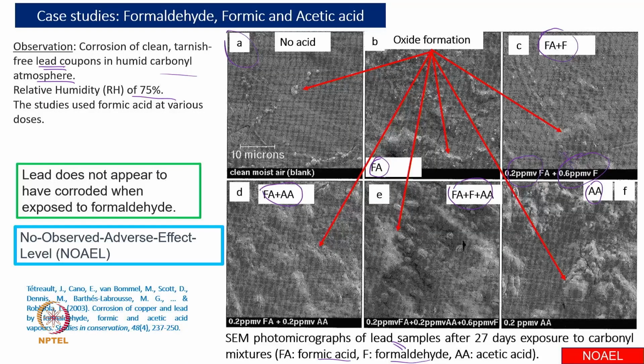Even though a very high concentration of formaldehyde is not affecting the surface, you can compare A and C and you do not find much noticeable difference. Between B and C, we also do not find much difference. Somewhat of a difference will come because formic acid has some effect on the lead surface. Coming to D, E, and F, we find the effect is more or less the same. So the main contribution is coming from acetic acid. Exposure to acetic acid is really affecting the surface.